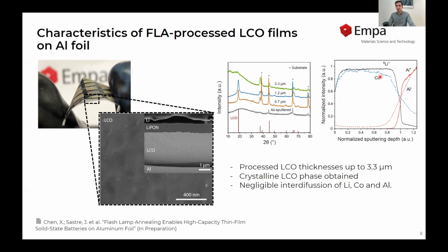We also did TOF-SIMS, time of flight secondary ion mass spectroscopy, to investigate the elemental distribution at the interface between the aluminum and the LCO to see if there is cross diffusion. One of the problems of thermal annealing is that there is a lot of interdiffusion from the aluminum foil into the LCO, and of cobalt and lithium towards the current collector. But since we are using this FLA method, the temperature at the interface remains below the melting point of aluminum, so there is low cross diffusion. This is what we observe here. The aluminum signal decays very rapidly when entering the LCO, and the same for lithium and cobalt signals. So this indicates negligible interdiffusion, which is a good sign for this technique.